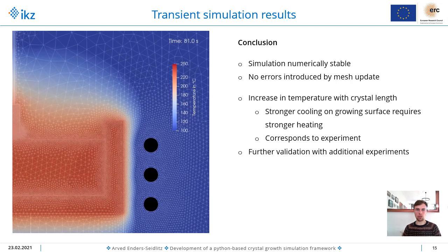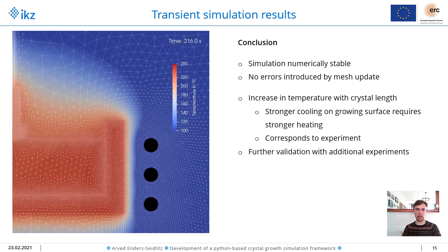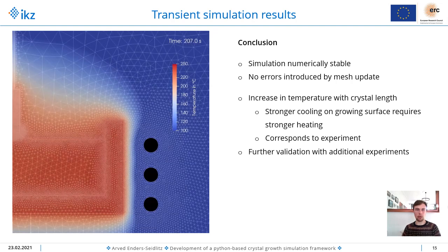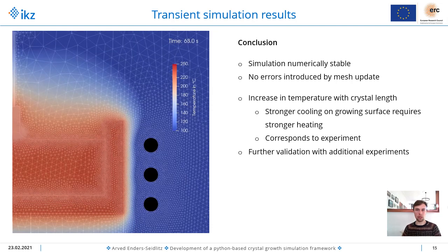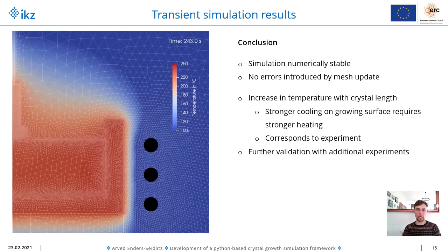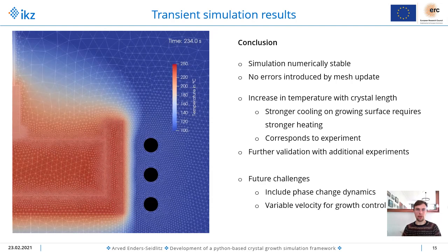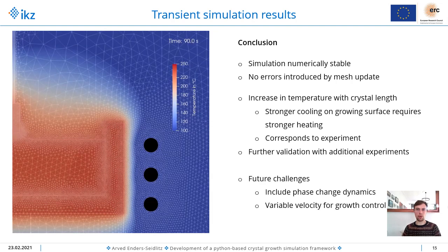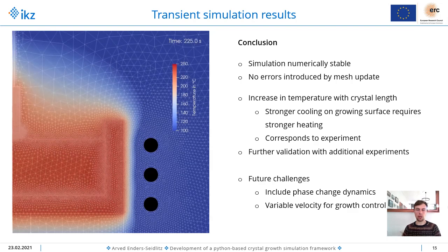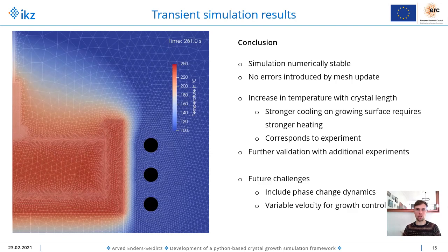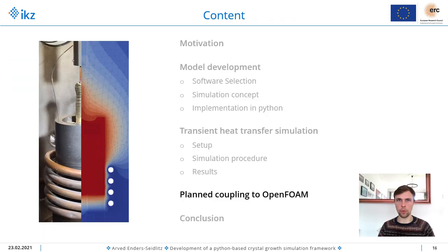The temperature, also shown in the video, is increasing with crystal length because of the stronger cooling at the surface of the crystal. This corresponds well to the experimental data, but of course further validation will be required. Challenges in future will be to include the phase change dynamics — not just using the steady-state phase change equation — and to allow for variable growth velocities. In future, we also want to include the fluid dynamics, and for this we plan to couple our Elmer simulation to OpenFOAM.